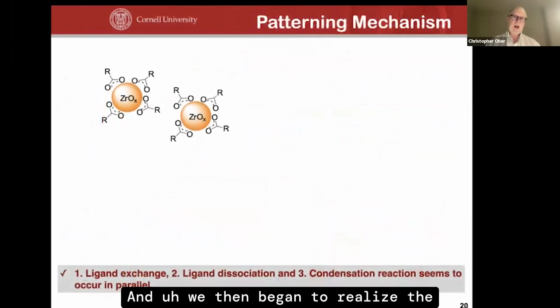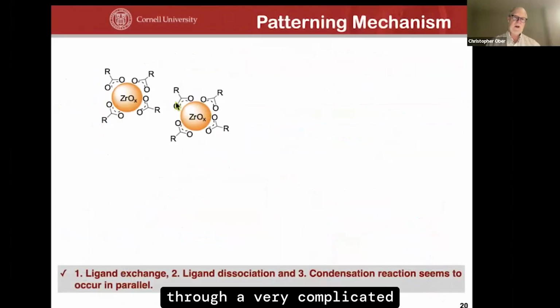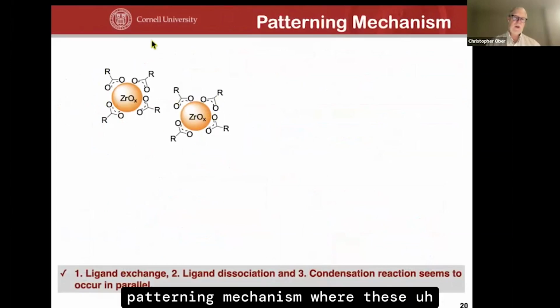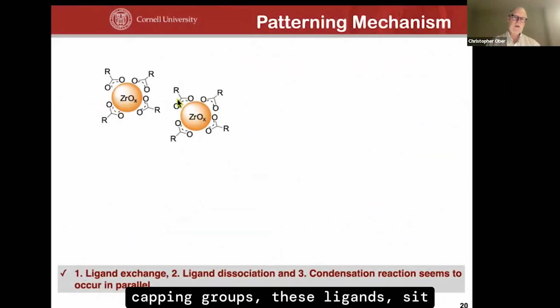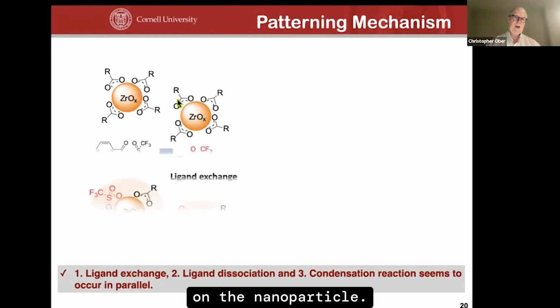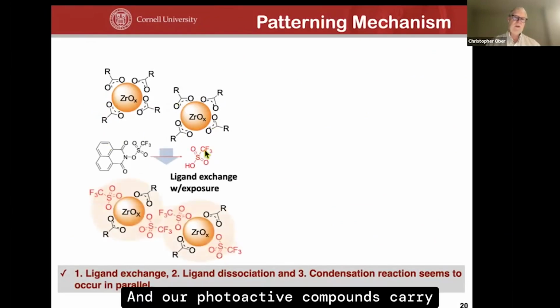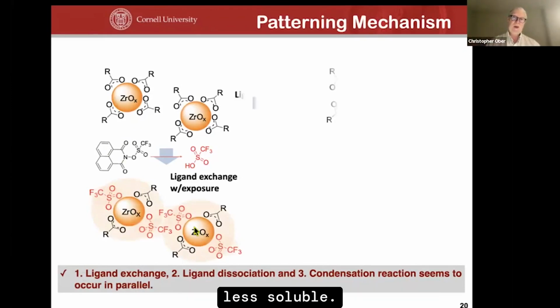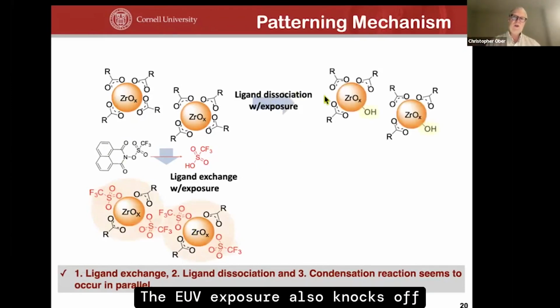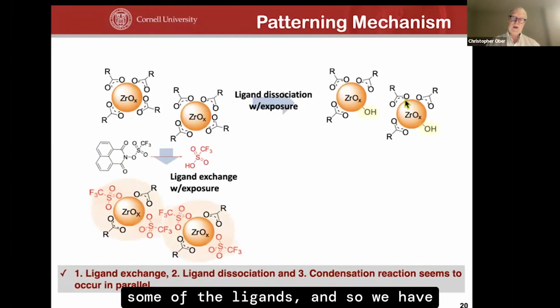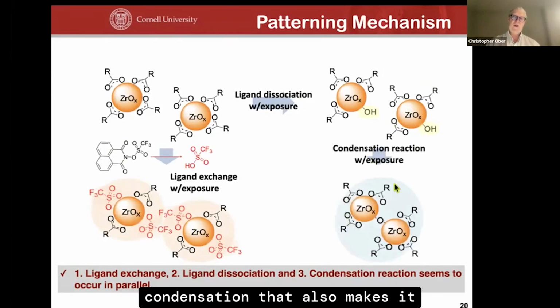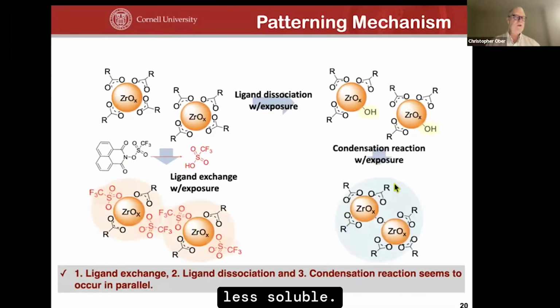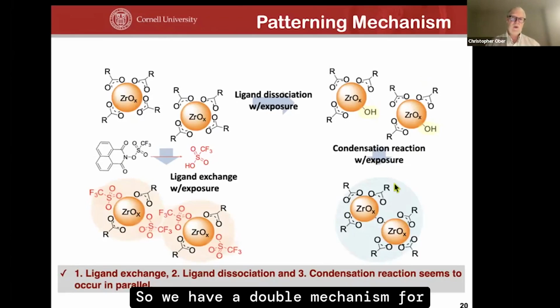We then began to realize the reason these could be patterned was through a very complicated patterning mechanism where these capping groups, these ligands, sit on the nanoparticle, and our photoactive compounds carry out a ligand exchange to make them less soluble. And the EUV exposure also knocks off some of the ligands, and so we have condensation that also makes it less soluble. So we have a double mechanism for producing negative tone patterns.